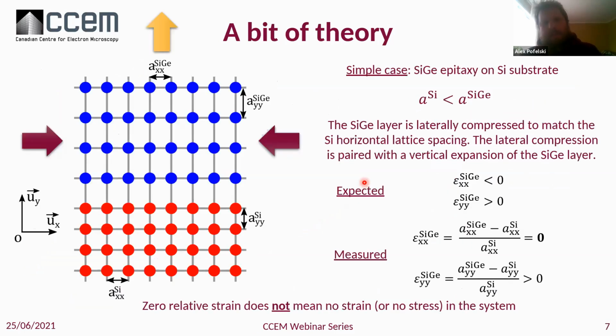But it happens that there can be some problems regarding the data interpretation. Let's see this very simple case, which is the silicon germanium growth on the silicon substrate. The silicon germanium at its relaxed state has a higher lattice parameter than the silicon. So to be able to realize this epitaxy, to have this lattice matching, this layer on top needs to be compressed laterally to have this lattice matching. And then after, the layer is going to expand vertically. So that's the very classic growth by, for example, molecular beam epitaxy.